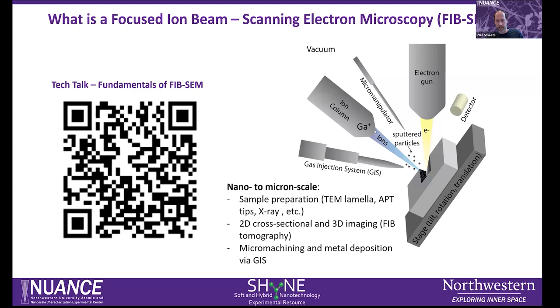With the ion beam in the conventional setting, like the Helios Nanolab I just showed you, we have gallium ions that can get emitted site-specifically, and you can remove material, so that's called milling or sputtering. With the electron gun, you can induce a variety of signals that you can then detect with a detector onto your computer and generate data that way.